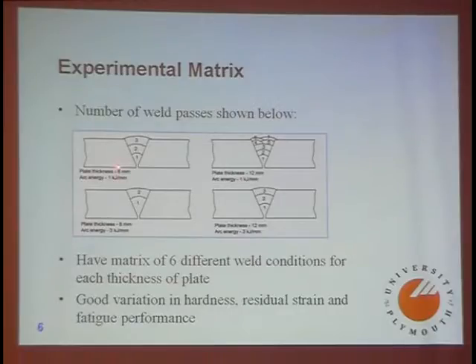This is 1 kilojoule per millimeter, 8mm plate, 3 passes. 1 kilojoule, 12mm plate, they're using 7 passes. 3 kilojoules, 8 plate, 2, and in that 3. So we've got a matrix with 6 different weld conditions for each of the 2 thicknesses. And as I say, that does tend to give you a good variation in hardness, residual strain, and fatigue performance. And so if you can find some way of predicting the fatigue ranking, there is a sporting chance that you're getting something true.